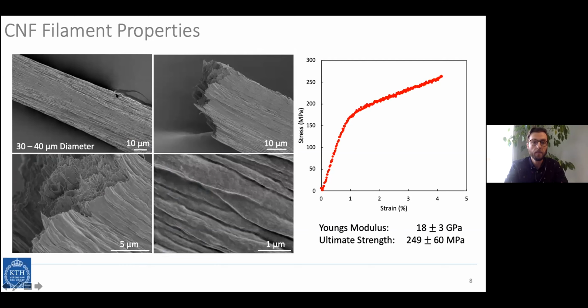So when we're starting to look at our filaments, we have a variety of data. We have SEM images where we have filaments after drying that are about 30 to 40 microns in diameter, which pretty accurately reflects a typical pulp fiber. If we look at it in a little bit more detail, we have aligned cellulose material along the axis of flow of these materials. And if we look at the surface of the filament, we can see that we have the wrinkling that we would expect to see on a cellulose fiber. If we look at the Young's modulus, we can see that we have a Young's modulus of about 18 gigapascals and an ultimate strength of about 250 megapascals. So we believe that these are good model systems for what we can expect from a variety of different types of pulp fibers.